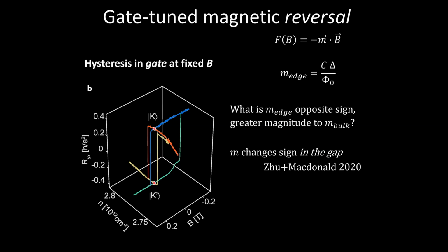The basic conclusion here is that in a small magnetic field, which is where we operate this, your system prefers to be in the ground state. The ground state means that the magnetic moment of your whole system should be aligned with the magnetic field. Now, clearly, if you change the sign of the magnetic field, you're no longer in the ground state. And if you have some metastable, irreversible dynamics, you will eventually relax to the ground state, which is now the opposite valley in this case.